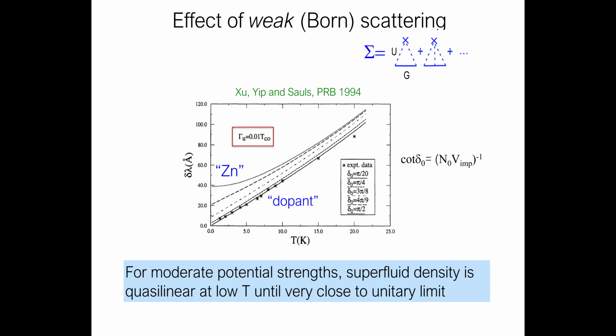And in addition, there's another feature which most people did not pick up on, although it's also been around for a long time, and that is that the crossover to the quadratic behavior depends a lot on the strength of the impurity scatterer. So if you're talking about a zinc sitting in the copper oxygen plane, that's a very strong scatterer, and it's probably close to the unitary limit. So it does induce this T squared behavior very rapidly. On the other hand, if you have a weak potential due perhaps to a dopant atom sitting away from the copper oxygen plane, the phase shift is much smaller. So you see that even for fixed scattering rate in this picture from Jim Sauls and collaborators back in '94, you could see in the weak scattering limit, what I labeled dopant limit, that it's pretty linear. So that's been known for a long time. So it's not clear that Ivan's argument necessarily works.